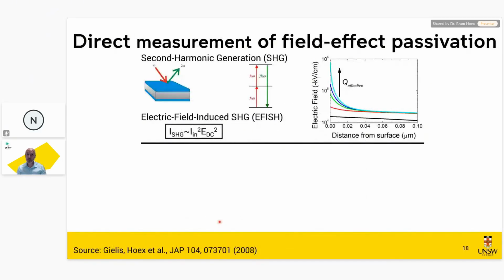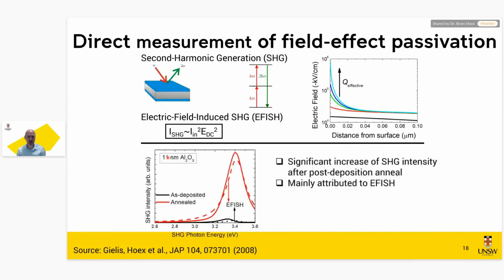And we actually already knew this when we first started working on ALOX. This is work that I did when I was still a grad student in the Netherlands, where we looked at a very exotic technique to measure electric fields in silicon. I will not bore you with the details. The only thing you have to take away is that we can measure electric fields, and that's exemplified here when we had a sample where in the as-deposited state, we knew that there was no fixed charge. With annealing, we could switch it on in the same sample, and we saw a massive increase in the EFISH signal, so the electric field signal.